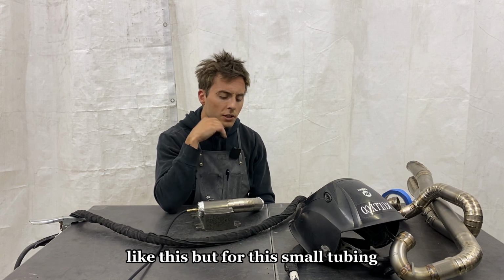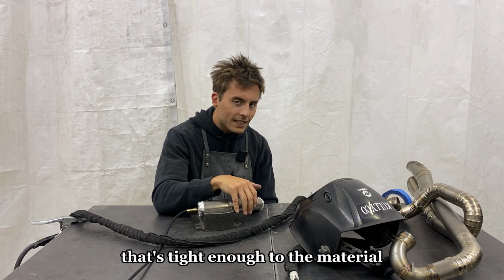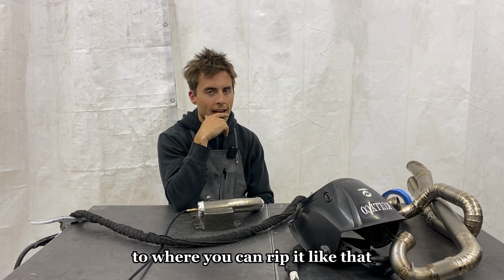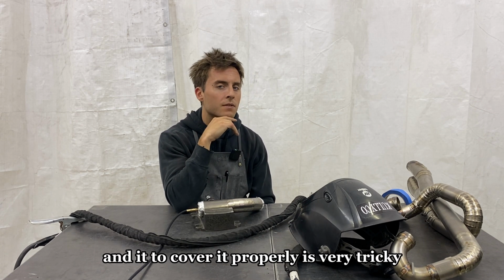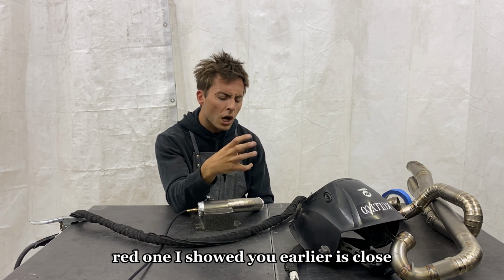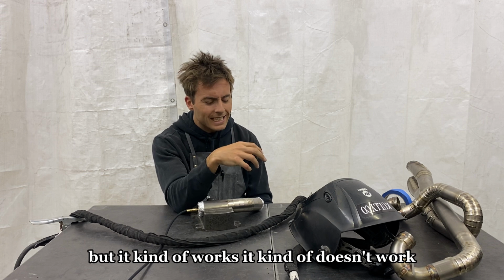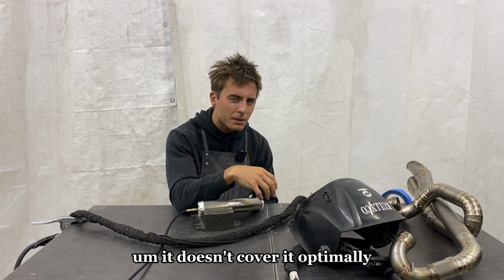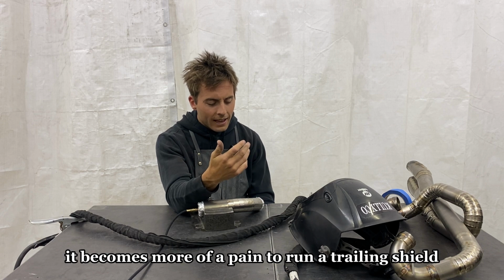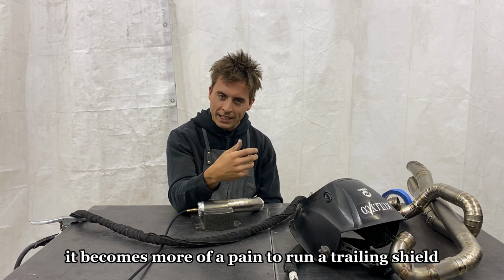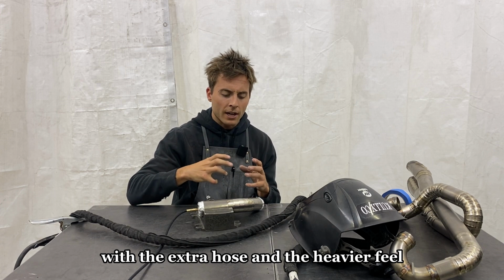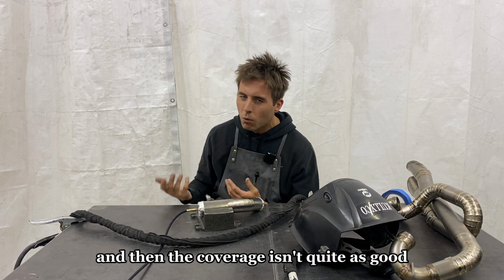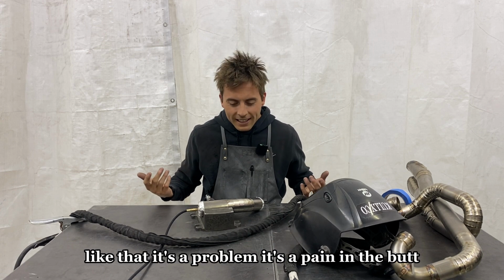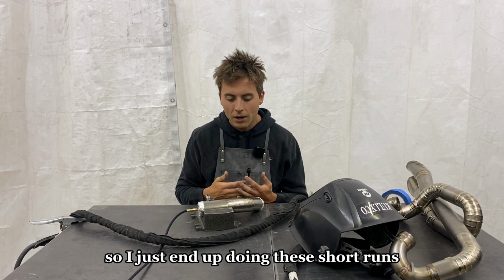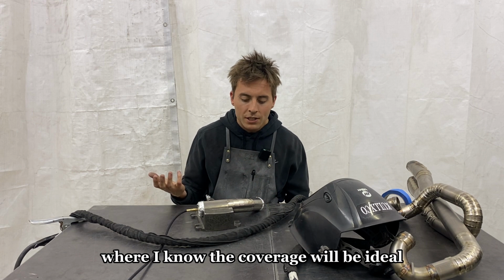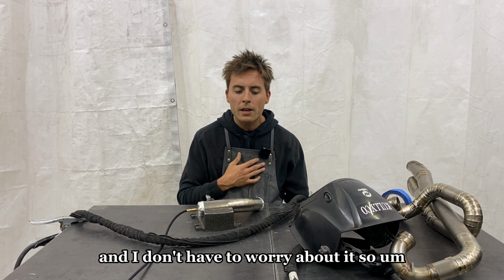But for this small tubing, finding a trailing shield that's tight enough to the material to where you can rip it like that and it covers it properly is very tricky. The red one I showed you earlier is close, but it kind of works, it kind of doesn't work. It doesn't cover it optimally all the time, and I've just found that it becomes more of a pain to run a trailing shield with the extra hose and the heavier feel, and then the coverage isn't quite as good. So I just end up doing these short runs where I know the coverage will be ideal and I don't have to worry about it.